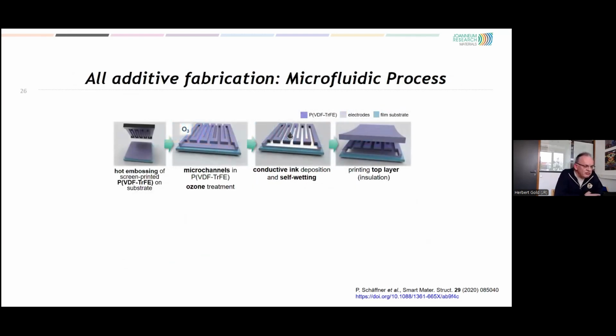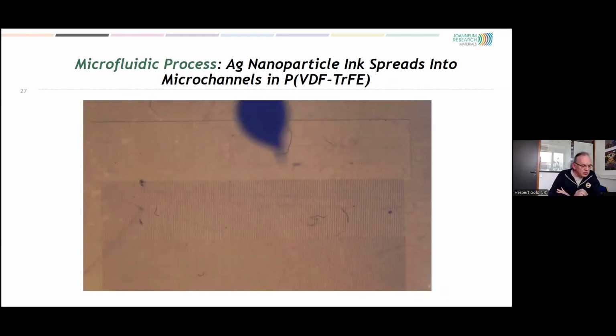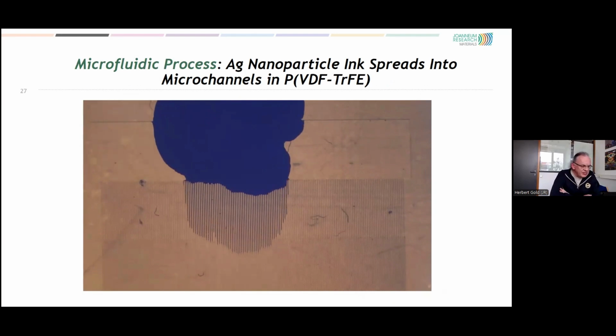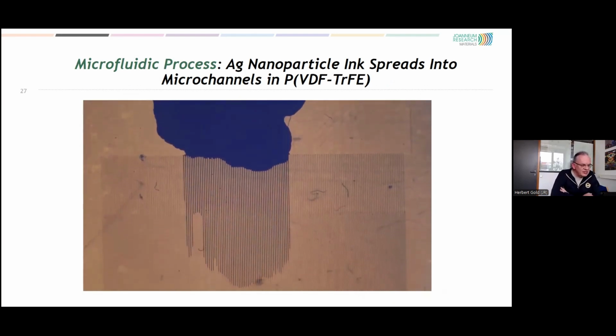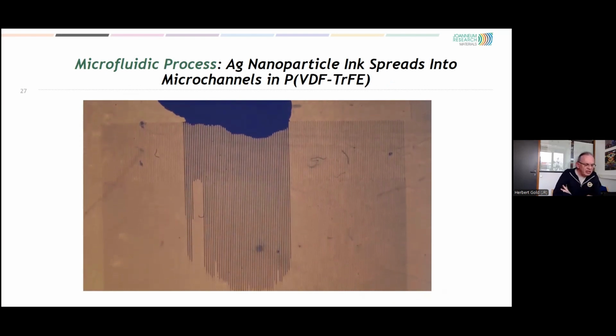And here is a fully additive fabrication. Hot embossing is a variant of the nano-imprint lithography. And we imprinted the PVDF by hot embossing and created these microchannels in the PVDF. Those were activated by ozone, because then the conductive ink would be deposited at the edge of these channels, and the channels would be filled by self-wetting or, say, capillary action. And on top, an insulating layer would be printed, and so we have a pure additive manufacture of metal electrodes. So this video shows how this goes in principle. You see this spill on top, so it's not a perfect one, but it shows nicely the idea of this additive manufacturing by capillary action.